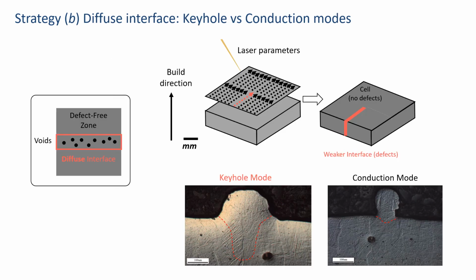The other strategy on which we have been working is the opposite, trying to generate a diffuse interface. So in this case we are trying to organize cavities close to each other to form an interface, but we are not trying to have something which is connected. And this can be done by using local laser parameters that in some cases will generate keyhole mode and the associated defect. And for the matrix we use the classical conduction mode so that we are able to locally organize porosity within the material.